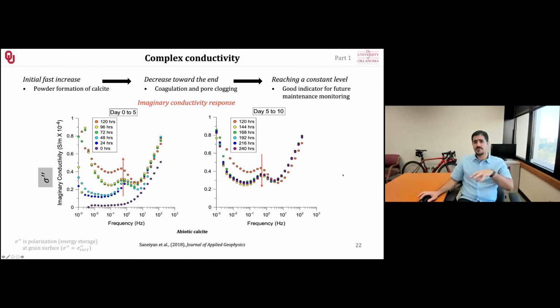Now, if you remember, I said that the imaginary part, the polarization part, the energy storage part depends on the surface area and the size of the pores and such factors. That basically tells you the more solid particles in a finer form you have, the higher polarization you get. I interpret it that, all right, initially the signal is going up because the calcite is precipitating in a powder form. And now, as we keep precipitating, these powders are coagulating, and that initial increased surface area because of the powder form is actually decreasing. They are connecting together and becoming larger calcite crystals, calcite coagulations.